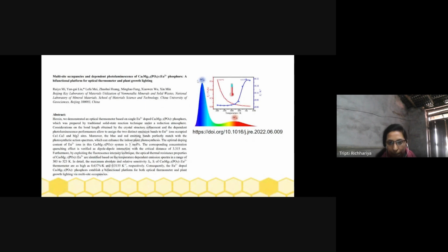Here in this spectrum, we can see that the dopant Eu2+ in the calcium magnesium phosphate can show multi-site occupancy. That means they are able to occupy the calcium site as well as the magnesium site. Due to the multi-site occupancy of the dopant in this phosphor material, they are able to produce dual emission. When they occupy the calcium site, they produce blue emission, but when they occupy the magnesium site, they produce red emission.